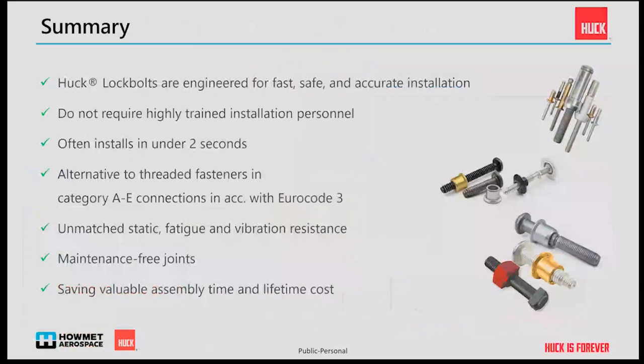So in summary, Huck Lockbolts are engineered for fast, safe, and accurate installation. They usually do not require a high level of qualification for the personnel. The training takes only a general introduction, a couple of hours or a one-day training to get used to the tooling and the fasteners. Installation usually is done in under 2 seconds, and the fasteners are suitable for category A to E connections in accordance with Eurocode 3. They have unmatched static, fatigue, and vibration resistance, and maintenance-free joints can be achieved using Lockbolts. There's no need to check the joints at regular intervals or retighten them, and this saves valuable assembly time, but also, especially for the customers, the lifetime cost is significantly reduced.